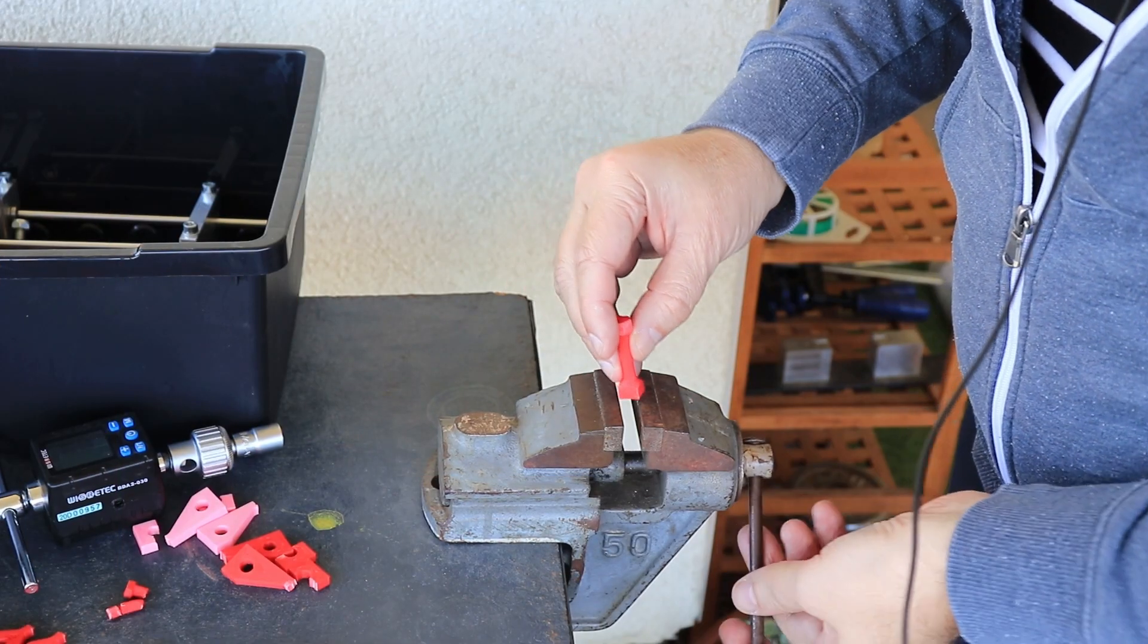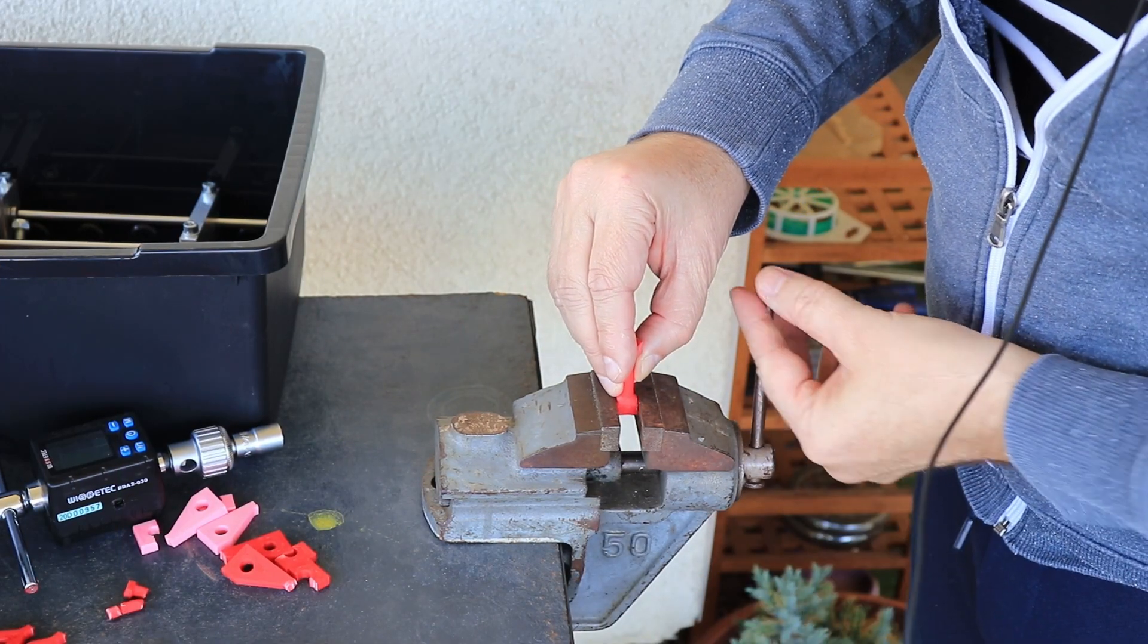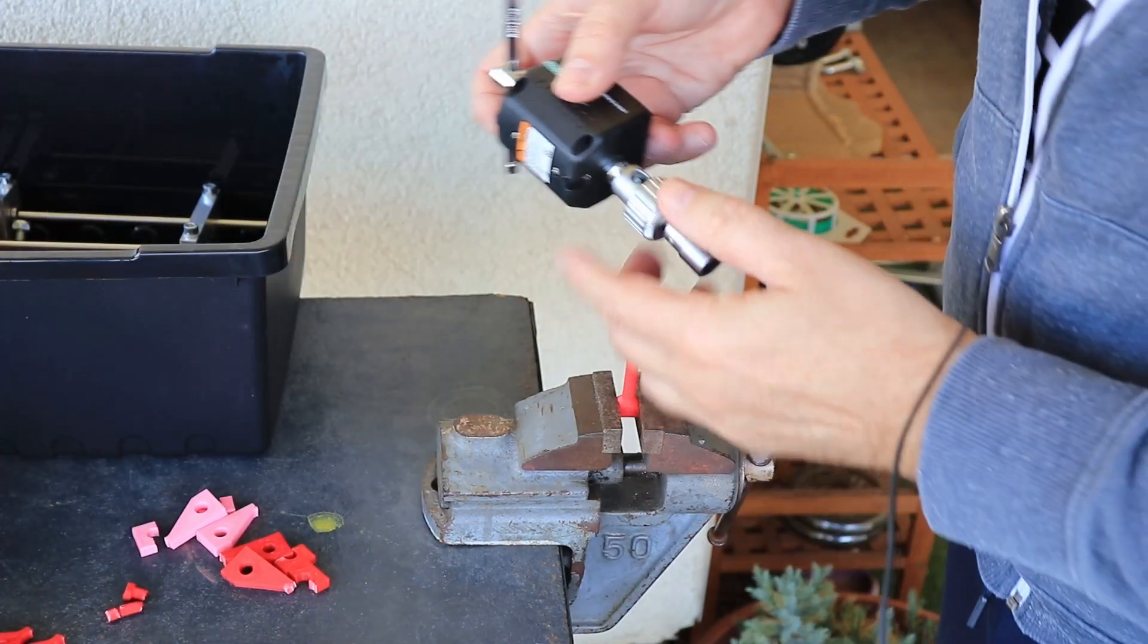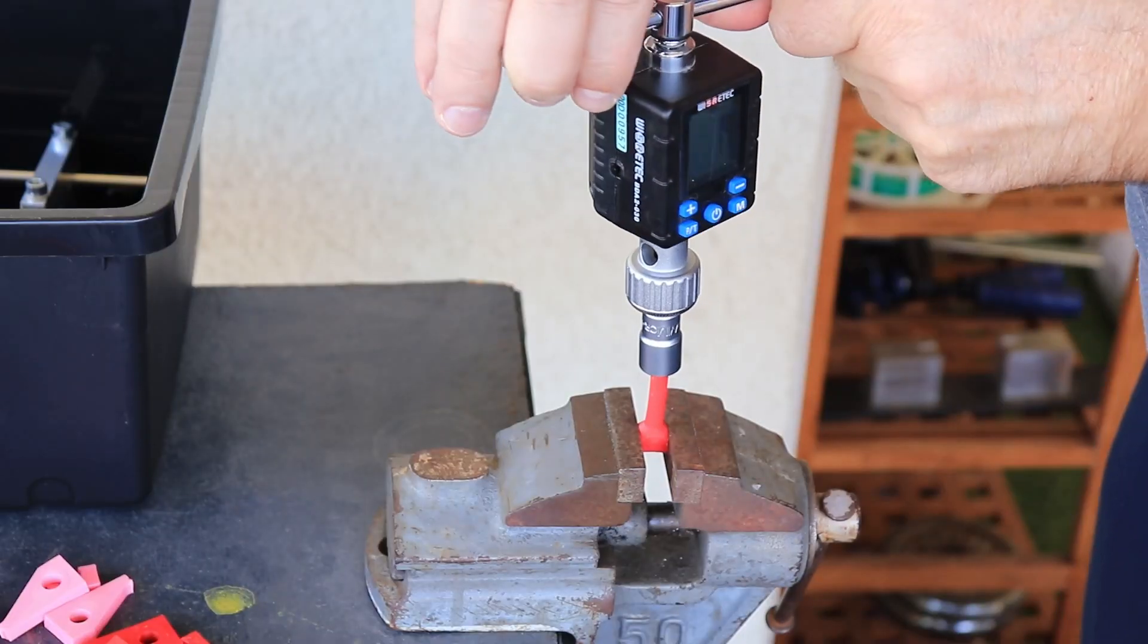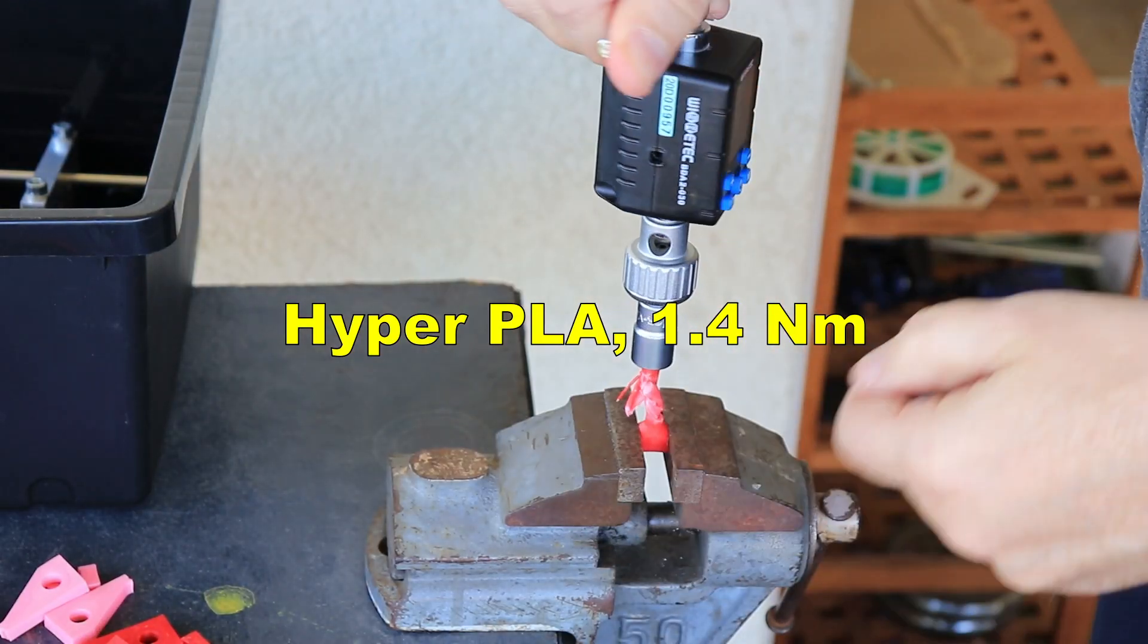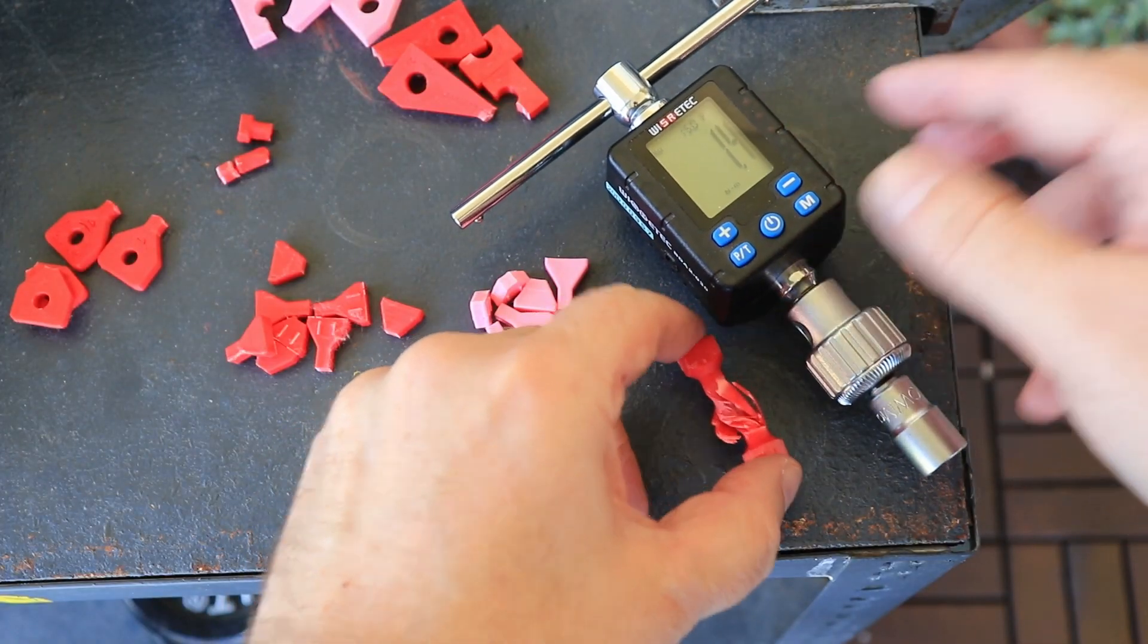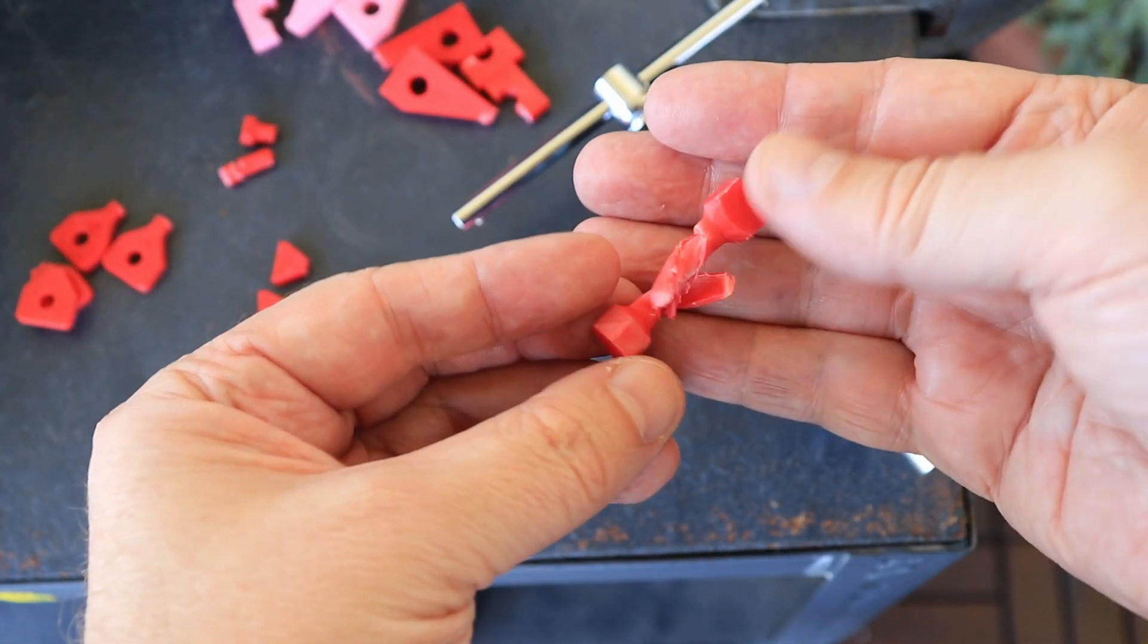The torque or twist test. The diameter is 6 millimeters of this test object and I want to record the load at 90 degree angle and the maximal load. 1.4 newton meter was the peak and also the load at 90 degree angle. Here you can see the test object.